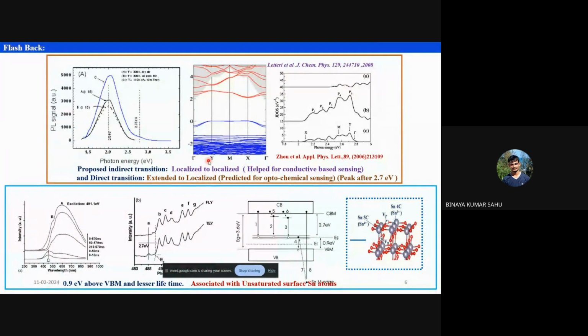So then we are telling that it is the surface structure and surface defect. And how can we prove that surface structure? There is one more technique that is known as XAS, the X-ray absorption study. Without going into the technicalities and the very enriched physics, what I will tell is, if you do the X-ray spectra of your material, and if you can see this kind of peak, in this comparison between two spectra, then if this peak is there, you can tell that it contains lots of surface defect. And if it is not there, it doesn't contain much surface defect.